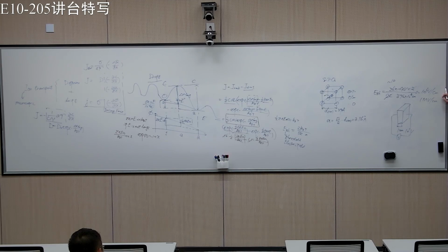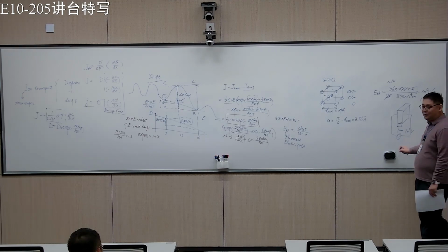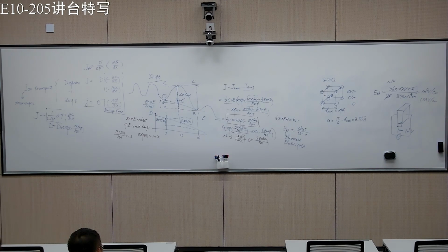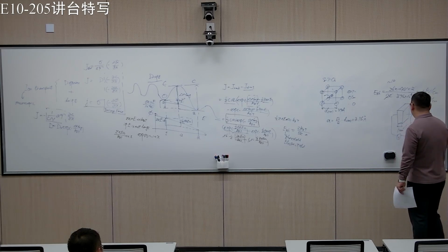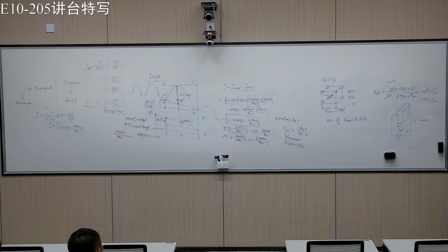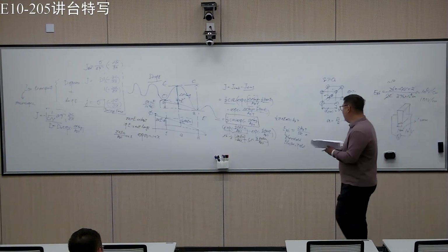So for any literature you see that claims they have a larger mobility or larger conductivity or larger diffusivity of ions because they have an electric field, you have to take a closer look at the literature because it could be very wrong. Okay, so the only case is that you have a 100 nanometer thin film. You can reduce the voltage by 2 or 3 orders of magnitude. Then it's probably better. Okay. All right.